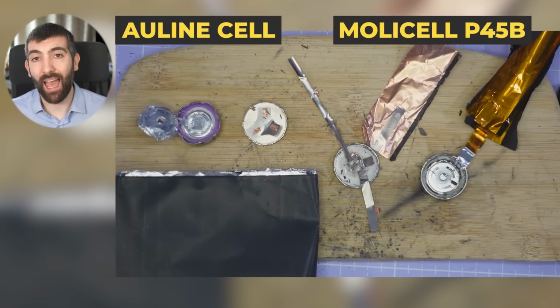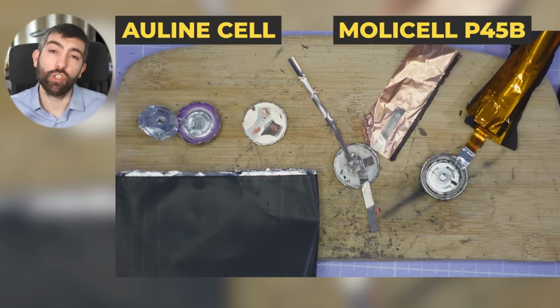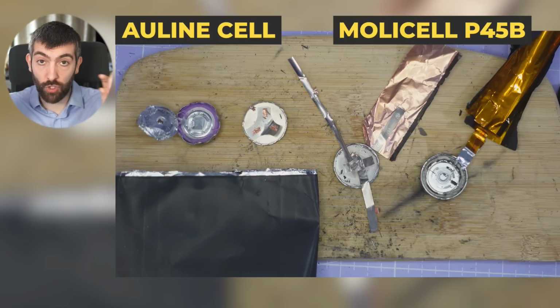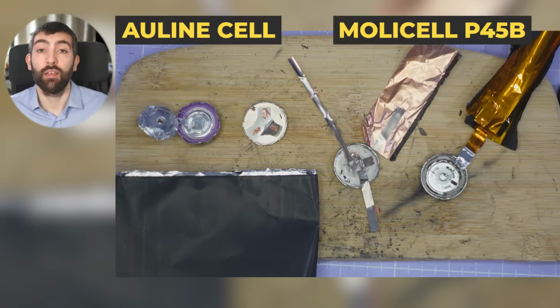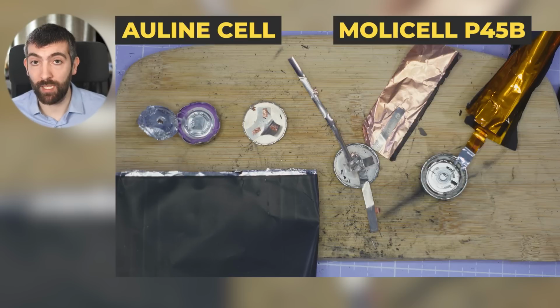between them. Starting with the Auline cell. The aluminium and copper foils on the Auline cell have an exposed strip at the edge of them. When the jelly roll is all rolled up, that exposed strip of foil sticks out of the top and bottom of the cell respectively. Those exposed pieces of foil are folded over and welded to an interposer, a nickel or aluminium interposer. That interposer is then spot welded to the negative and positive terminal of the battery.